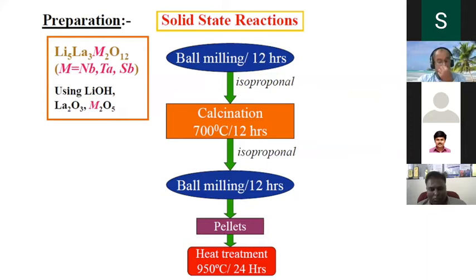Then a group in Kiel started to prepare these materials like niobium, tantalum, and antimony, focusing on the niobium and tantalum. Initially, by means of solid state reaction, just mixing together, calcining at 700, and again ball milling, and then heating at 950 degrees Celsius for 24 hours, they were able to synthesize this material.